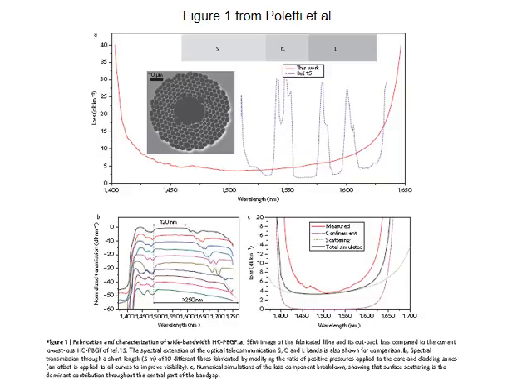In B, authors show the transmission window for 5 meters of fiber, obtained by changing the experimental conditions, mainly pressure, of the fiber preparation. In C, the relative contribution of light confinement and scattering to the total calculated loss. The main contribution comes from surface scattering.